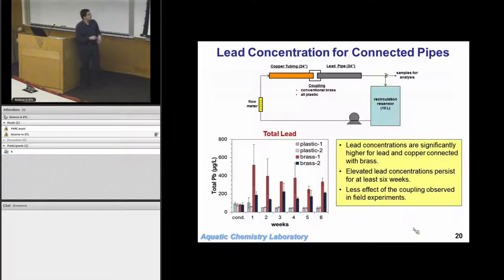And there were some big questions about this, so we got involved in this, and we did some experiments up here on the first floor of Brower Hall, where we took lead pipe, we took copper tubing, and we connected them with brass fittings and with plastic fittings. So the brass fitting is electrically connected, so that copper and the lead are connected. They can act as a battery to have galvanic corrosion. The plastic, that can't happen. These are the lead concentrations down here over time for 6 different weeks. The lighter colored points are what we saw with plastic coupling. The darker ones are what we saw with the brass coupling.